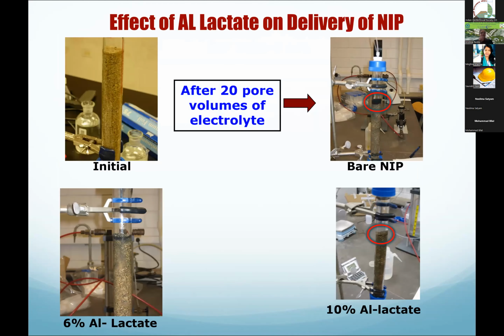Now you see that one. Now, I want to see whether these dispersing solutions will help in transporting the contaminants. So initially, I had sand in the column, and we put a slug of the nanoiron particle, non-amended, just a bare NIP. After 20 pore volumes of the electrolyte solution, still nothing happens to this one. Just the electrolyte passes through, and we collect it, and no iron can be seen in it. But if I use the 6% aluminum lactate in the nanoscale iron, and put that on the top of it, and then I flush the water, then you see that one.